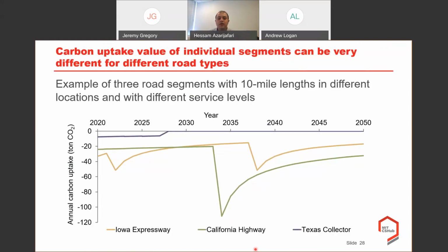So you can see that the collector in Texas obviously has a smaller surface area. Therefore, the carbon uptake is quite smaller, and the age is maybe 35. So most of the carbonation has already occurred. And as we go forward in time, we don't see that much extensive carbonation. And up to the year 2027, here we have a composite asphalt, an asphalt overlay on top of the concrete, which will avoid any carbonation in the future because the concrete surface is totally covered.